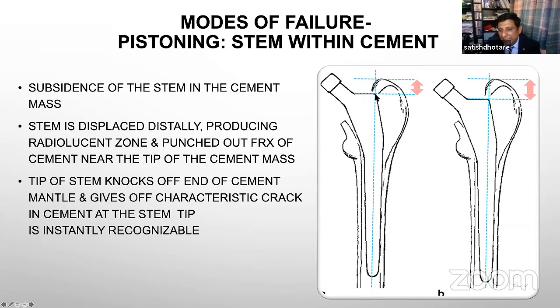Now this is the shoulder of the stem, and this is the trochanter. If you measure this distance in the serial follow-up X-rays, you will be able to assess how much subsidence this stem has got. And as I said, if it is more than 5 millimeters, that means the stem is loose, or there is more subsidence. That means there is some breakage in the cement mantle, and you need to look all around the prosthesis. That causes instability, which will lead to sclerosis and thinning out of the cortex on the lateral side with the tip of the prosthesis with stem in cement.